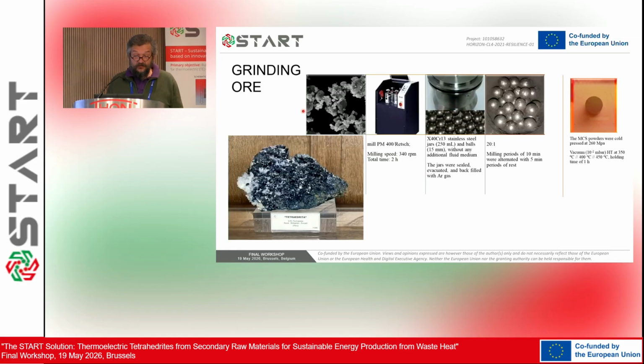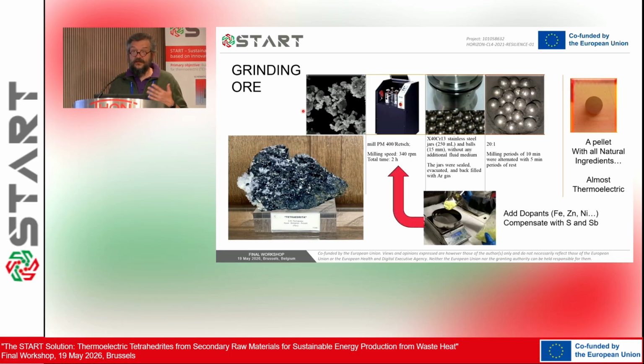In any case, we cannot simply grind the ore and pretend that we arrive at the end with working thermoelectric materials. It's almost thermoelectric, because minerals are always different, and this target composition that we have is basically never present in nature. So we need to add the dopants, add the iron, the zinc. In some cases, we also tried nickel, and compensate our addition for the sulfur and antimony.